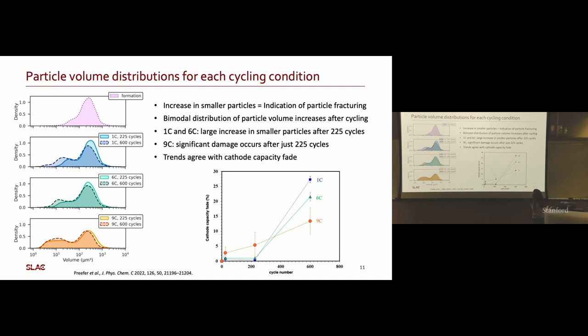And there's a bimodal distribution. So actually, 1C and 6C have the largest increase in smaller particles after the 225 cycles compared to the 9C. 9C actually, there's not much difference between 225 and 600. And so we attributed that to the damage basically already being done at 225 cycles at 9C. And so those extra cycles don't actually contribute more to particle fracturing.